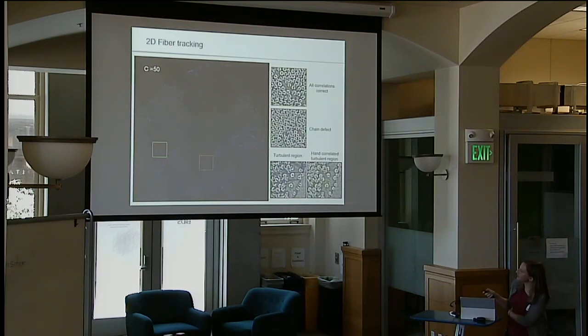And this diagram shows the vectors for every single correlation between the fibers. We find that it's usually about 70 to 80% successful. There are several regions where all of the correlations are correct. However, there are several regions where there are different types of defects. And the two that we've been dealing with are, the first is a chain defect. So in this case, if one fiber is identified wrong, this will just propagate down a line of fibers that are then all incorrect. And then the other challenging regions are turbulent regions, where there's a significant amount of fiber movement, and the algorithm has a hard time tracking those fibers as well.